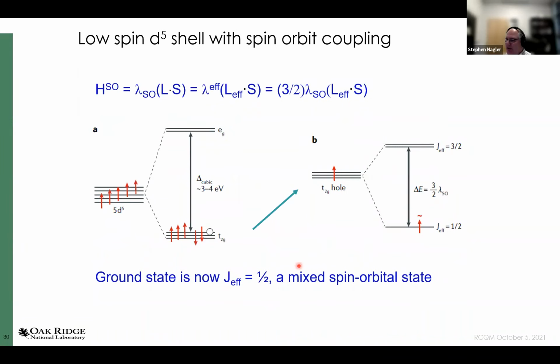So, if I think further about this, if I have spin orbit coupling, this T2g level, which has given me an L equals 1 effective and an S equals 1/2, will split into manifolds of J. I prefer to think of this in the hole, if you like, picture. And I have a ground state that has an effective J of 1/2, doubly degenerate. And it's a mixed spin orbital state. And as we'll see, a mixed spin orbital state is really what is needed in order to get anisotropic exchange interactions.